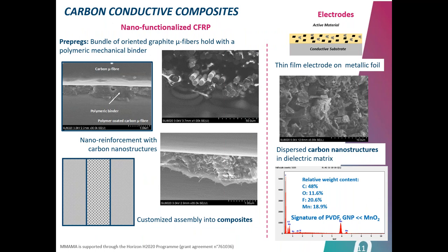So you have prepregs composed of carbon microfibers bound with a polymer, and upon the roll-to-roll process, Adamant Composite is reinforcing the electrical or conductive properties by adding some carbon nanostructures. This is on the left-hand side. On the right-hand side, you have the typical electrodes based on a mixture of carbon nanostructures with other materials that has also been characterized at Materia Nova.